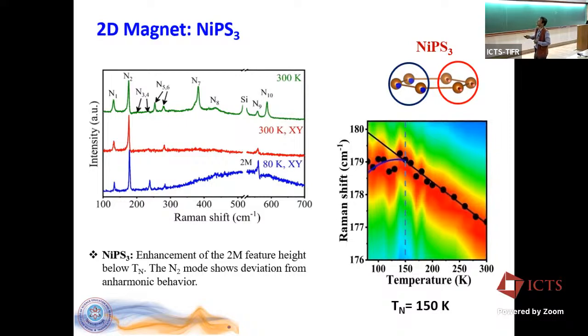One is in the form of a magnon, rather 2 magnon, which is a broad hump seen somewhere around 500, 600 wave numbers at low temperatures. And that has a very interesting story. If I get time, I'll probably touch upon that. Now, as we go to higher temperature, of course, you see it has decayed significantly. But at the same time, there is another mode, which is the N2, the second one here. Okay, that shows slight asymmetry, and it shows a splitting. So those are the 2 signatures which people look for in the antiferromagnetic ordering.